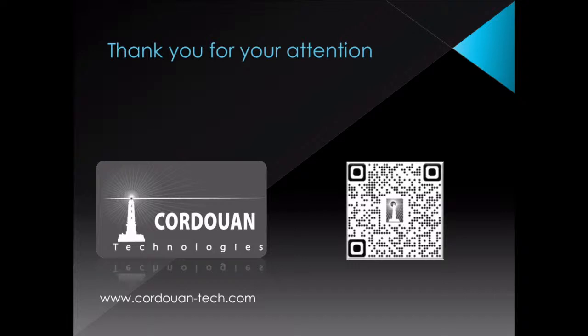And the idea is, first thing is that when you have spherical nanoparticles, you don't have any photons coming, or very few photons coming on the horizontal polarization. As soon as you have an anisotropic nanoparticle, you find a lot of photons coming on. So first, you have a way to detect if you have anisotropic or spherical nanoparticles. But more than that, thanks to some good calculation, and good mathematics, we are able to come back to the length and the width of nanoparticles.